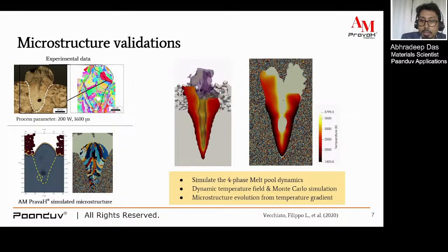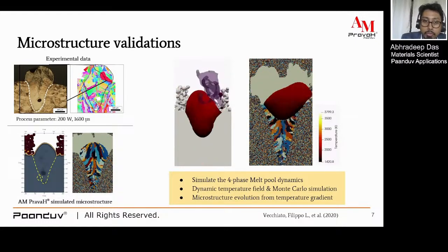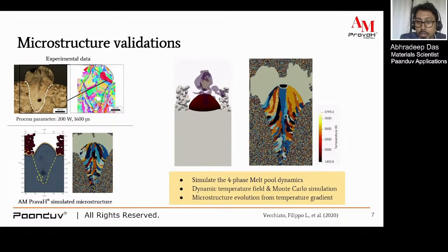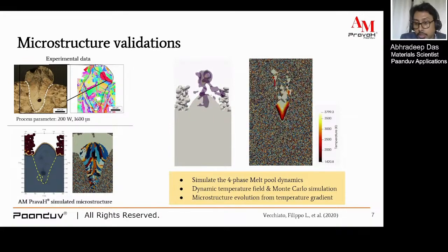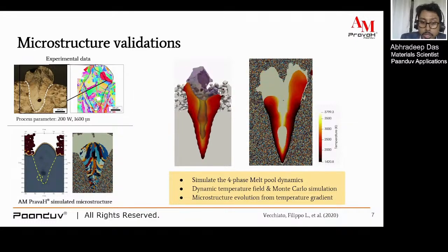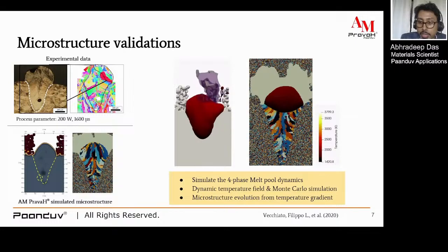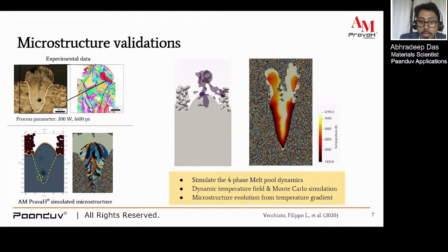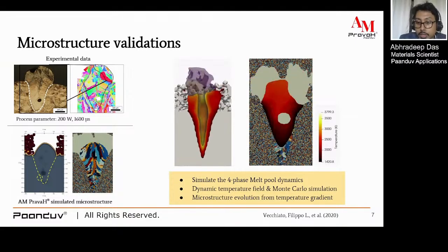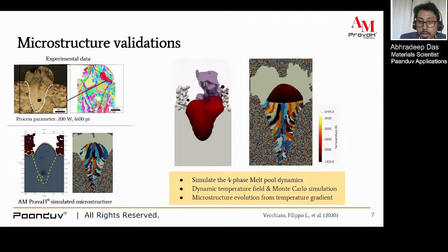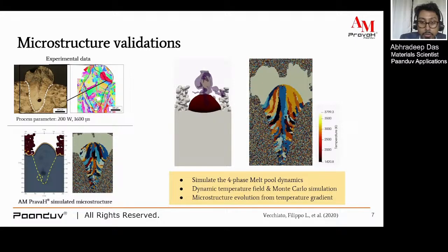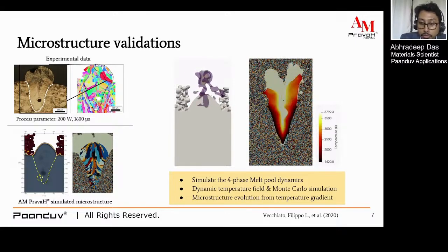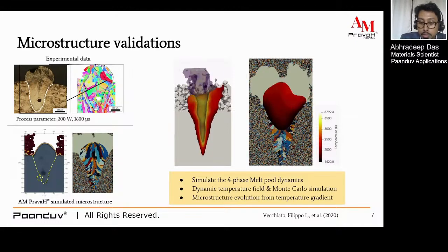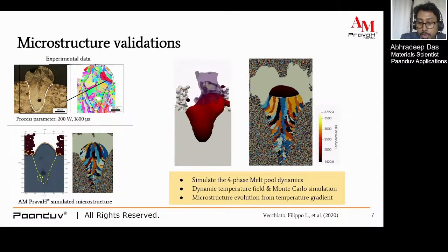For the microstructure, it is one of our interesting modules. What we have observed is that the process parameters govern the microstructure formation, which eventually leads to the formation of different properties. So this is what you can see here, and how exquisitely we have captured those areas which are left over in the experiments. That's how we reduce the reliance on experimental exhaustion for researchers across the globe and for the engineers who have been working in this particular field. We use in parallel the four-phase multi-phase problems along with different Monte Carlo based models to model this microstructure solution.